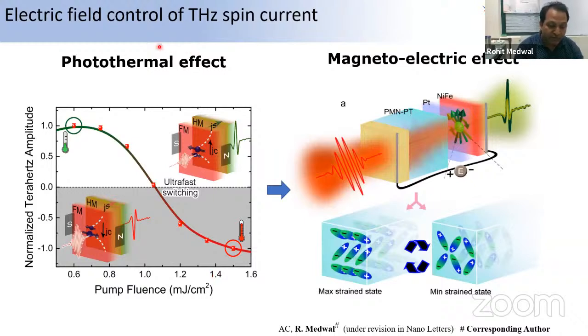And we also try to develop a new model to do the switching, not only optically but through magnetoelectric coupling, where we're trying to design these emitters on a PMN-PT substrate, which is a ferroelectric substrate, and see how we can control the terahertz field using a pure electric field. This is really an application part, because we cannot come with a laser and then develop a bigger system where we modulate these spintronics emitters using purely optical light.